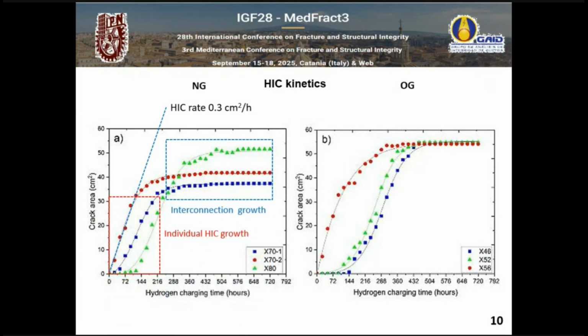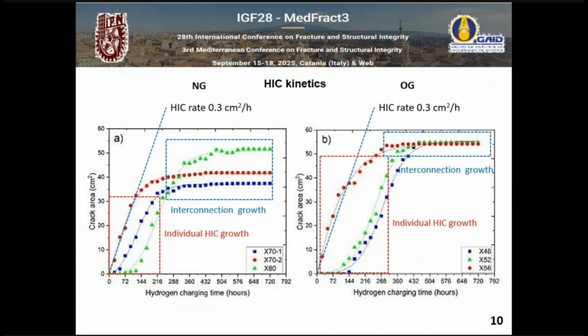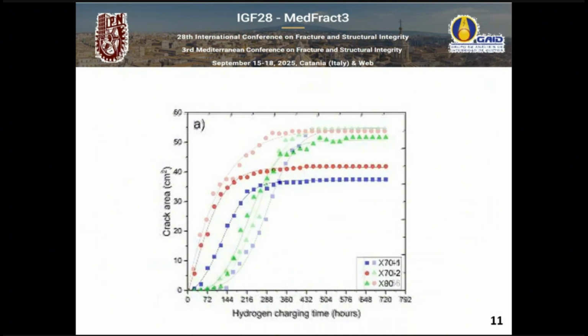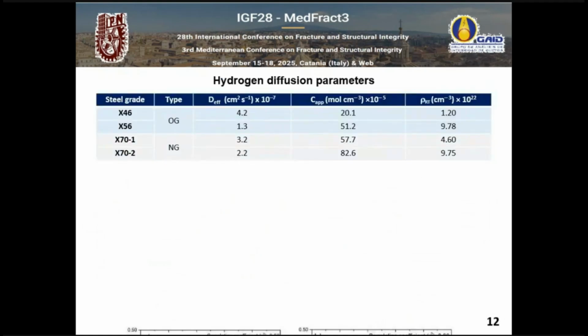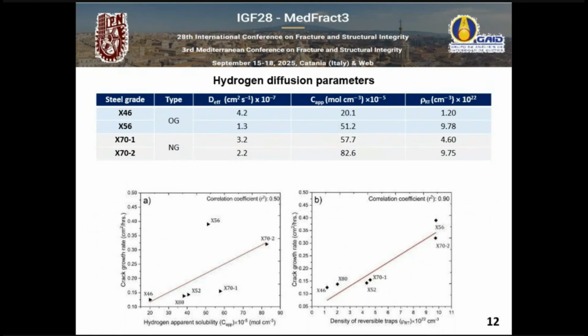We measure the crack growth rate in the individual stage, and you can see it's much faster than in the interconnection growth. But if we overlap these two graphs, we see that the new generation and old generation in the individual growth stage have very much the same behavior. The only difference is in the final total cracked area. So we try to correlate this with the diffusion parameters, and as you can see, with respect to the hydrogen solubility, we don't have a good correlation, but if we measure the density of reversible hydrogen traps, we have a good correlation. But if we separate this data by microstructure, then the correlation is much better.